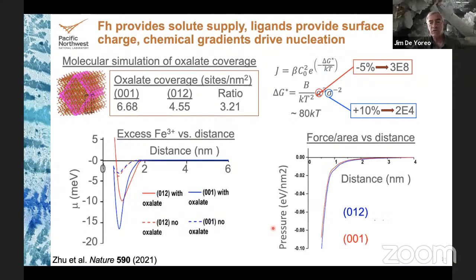And once those particles form, you can ask, what is the barrier to attachment? And the answer is there isn't one. They're forming in the 1 to 2 nanometer range, and what the simulations show is it's an attractive interaction directly to the surface. They're strongly pulled to the surface, and that's the way in which these form.